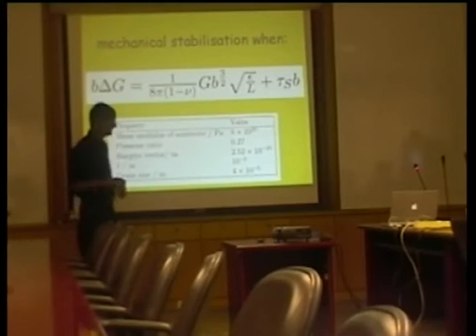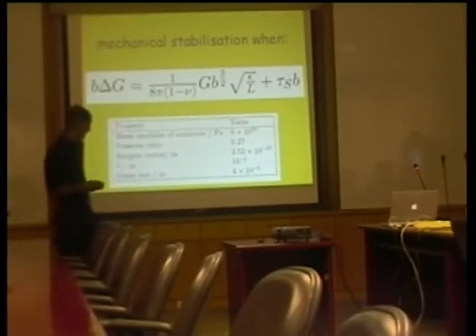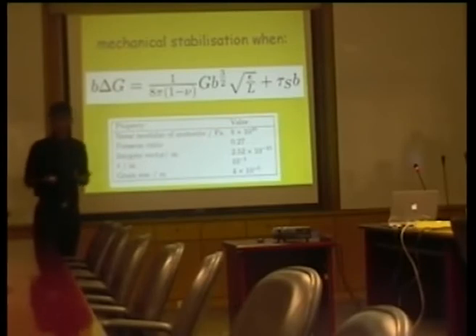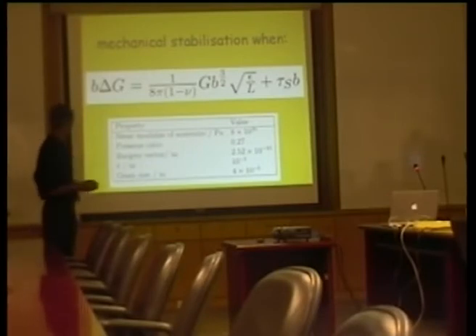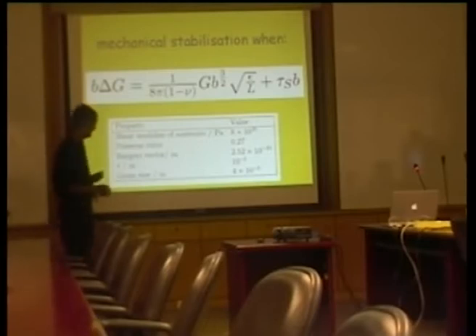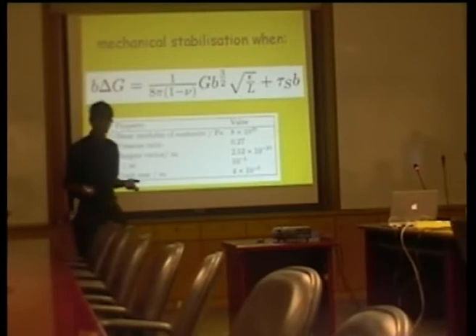and we can work out the strain required for mechanical stabilization. And this is just to illustrate the numbers that we put into the theory. There are no adjustable numbers here. So we have the shear modulus of austenite and the Poisson's ratio, which are standard from the literature. We have the Burgers vector of dislocations and the grain size parameters. So this is the starting grain size, about 40 micrometers.